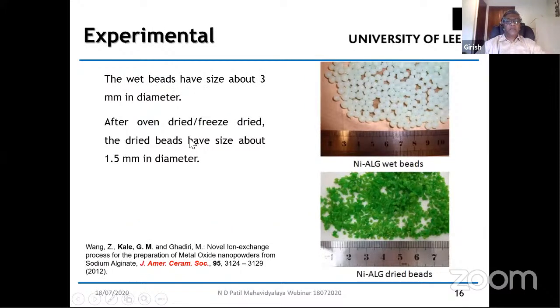So this is an experiment that we did quite a while ago. This was the initial stages of trying to prove the technique, which was done in 2012. We published some of our work in this particular paper in 2012 on nickel oxide. So we produced nickel oxide. Now, nickel oxide, again, we wanted to investigate because it has applications in solid oxide fuel cells as a component of anode material. So we looked at nickel oxide, and what you see here is the nickel ion exchange beads with sodium alginate, and you have the dried beads, which are very green, which is a typical color of nickel. So you can see that they're very nice green color beads, dried beads.